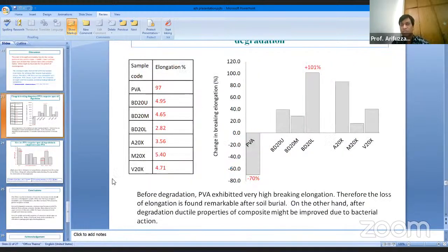The figure shows the elongation property of composite after degradation. This table shows the elongation property before degradation, and the figure shows the loss of elastic property after degradation. We show that the loss of elongation is highest for pure polyvinyl alcohol. On the other hand, the elongation increases after degradation. Before degradation, polyvinyl alcohol exhibited very high breaking elongation. Therefore, the loss of elongation is remarkable after the soil burial test. On the other hand, after degradation, the ductile property of the composite might be improved due to bacterial action.